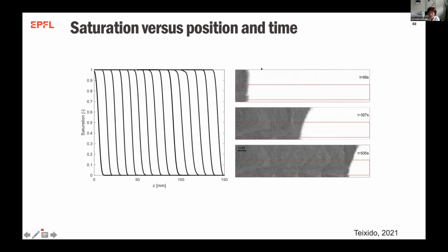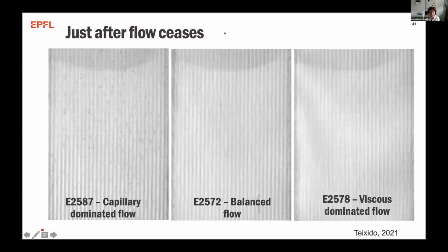And then you can really extrapolate the saturation curves for different cases. And just after the flow ceases, you can also see, and this is with a contrasting agent to improve the contrast here, but you see in the capillary dominated flow, after we stop the flow, you see a lot, I have to put my laser pointer again, a lot of voids remain. So we can also use this tool to measure how the voids concentration evolves with time after we finish the flow. The balanced flow, we see that it's actually very good with a little porosity.